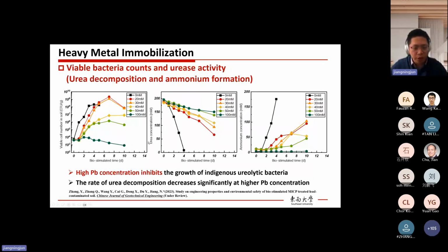Then if we look at the urea concentration change with time, because this one could give us an idea how fast the urea has been decomposed. Okay, for the no contaminant case, it is decomposed very quickly. After 4 days, almost no urea left. So it means that stimulation works very well in this case. Then even with 20 millimole, a little bit of contaminant, we can see the urea decomposition has been retarded, even a little bit.